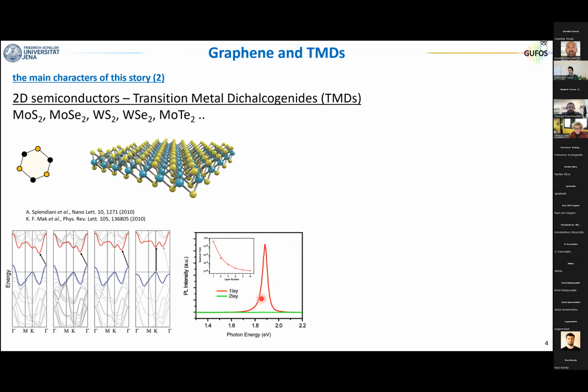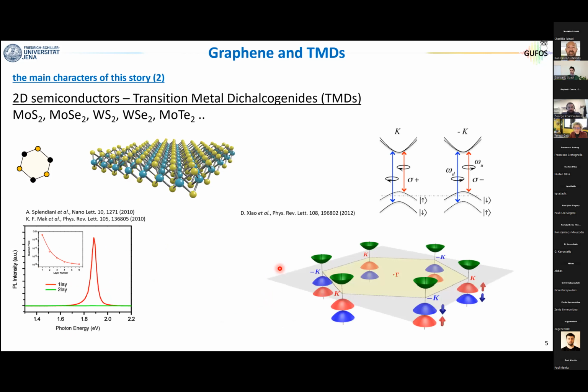And this is something that you can test or prove by looking at the photoluminescence of the material. Because of course, when you have a bilayer and an indirect gap, the light matter interactions are weak, the photoluminescence, so the light emission, is close to zero. And instead, when you go to a monolayer, you have orders of magnitude enhancement in the light emission or luminescence of the material.